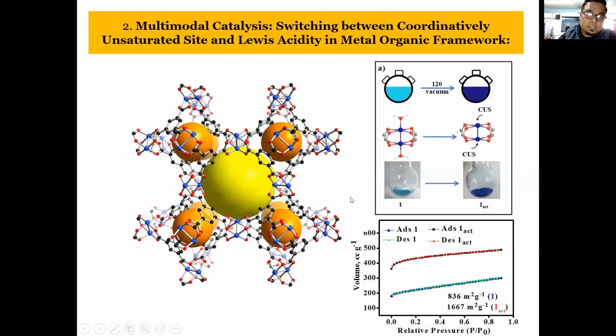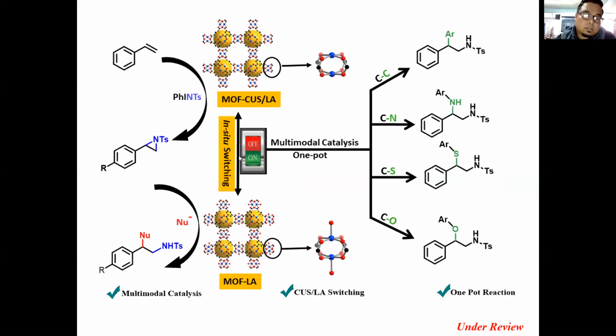Now while changing into these two forms, what we could understand, where we used this system, is we designed some reactions. For example, we have an alkene system here where we can introduce a nitrogen and make aziridines, cyclic nitrogen compounds, right? This reaction can only be catalyzed by the activated one, meaning the copper ion which is devoid of water. Whereas there are other reactions where this nitrogen cycle is opened by a nucleophile and you have a ring opening product. This reaction can be done by either the activated or unactivated metal organic framework.